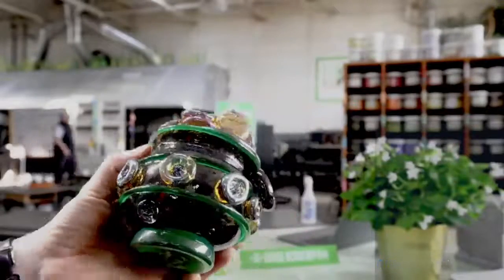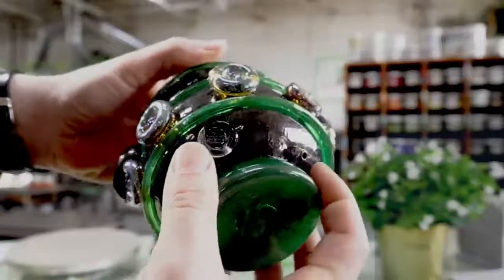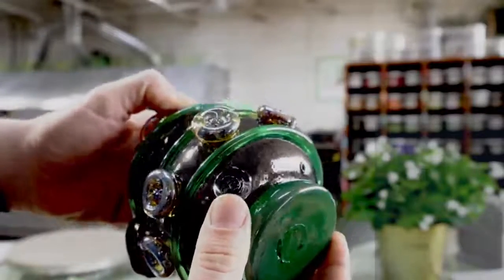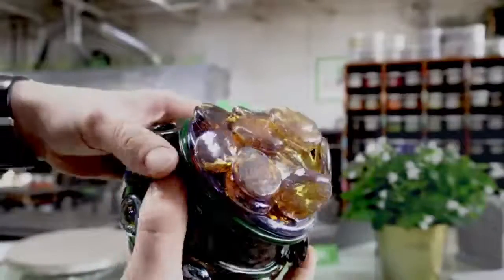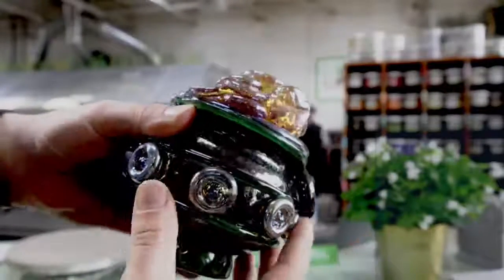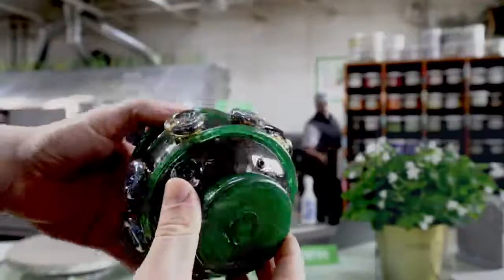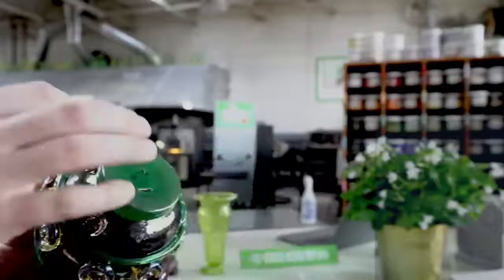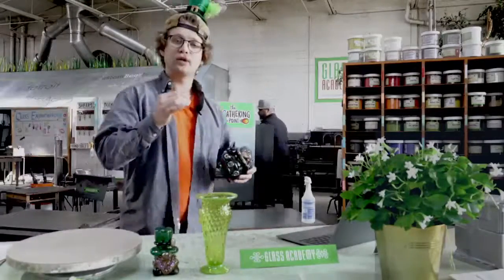Super clean. Something else that's really cool. We got the GA stamp on the bottom, but you see that tungsten hole right there. We talked about that on the show, and we showed you how that went down with tungsten metal. Bored a hole into it because when we put this big flat gold patty on the top, we sealed air inside of the cauldron. And so we didn't want the glass expansion and contraction to put too much pressure within the piece. So by relieving that pressure, all we do is bore a little hole into it.